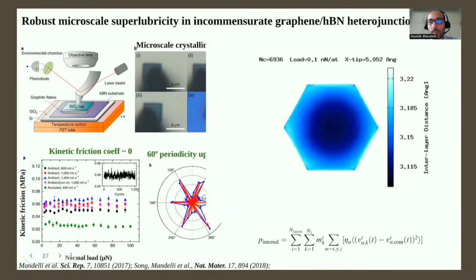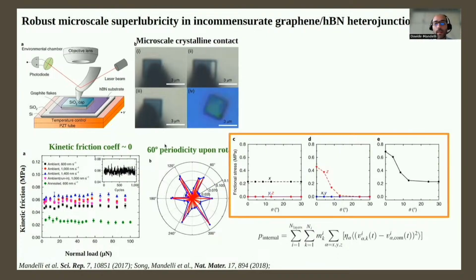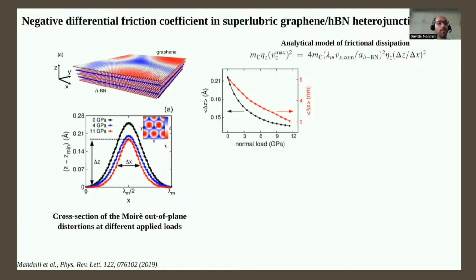And I would like to show you the propagation of this mass density wave within the flake, in this case, upon sliding. So the propagation of these moiré ridges is what leads to dissipation under sliding and to this anisotropy of friction.